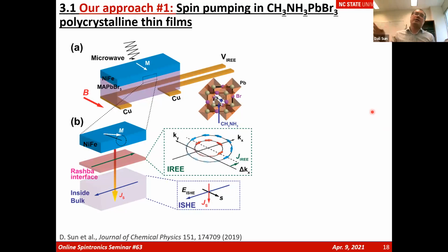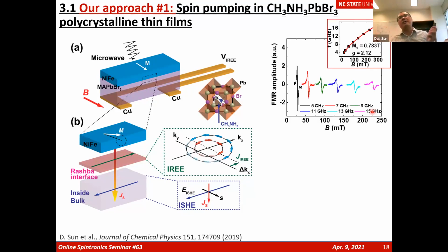We're doing this in a polycrystalline thin film. We spin coat the MAPbBr3 thin film, a solution process, and deposit nickel iron on top, forming a bilayer structure. We shine the microwave, introduce a spin wave in the ferromagnet, and inject spin current into the hybrid perovskite materials. If our hypothesis is correct, we may see the inverse spin Hall responses from both contributions, also the surface contribution, which can be attributed to the Rashba interface.